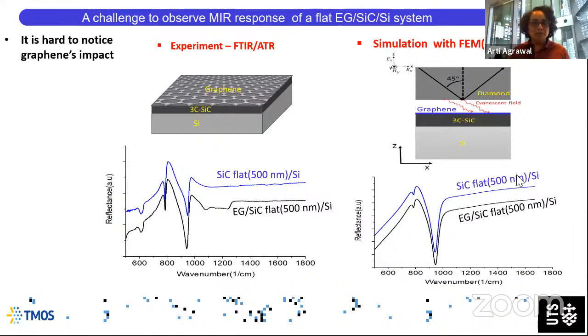If we look at the experimental results of FTIR, and we look at the reflectance from the structure, we see that the plain silicon carbide, which is represented in blue, has this particular dip around 950 centimeter inverse, and a peak in reflectance around 800 centimeter inverse. Coating it with graphene gives us the black curve. And there isn't a shift in these features. They stay roughly the same. So we can't really notice the impact of graphene in the structure.